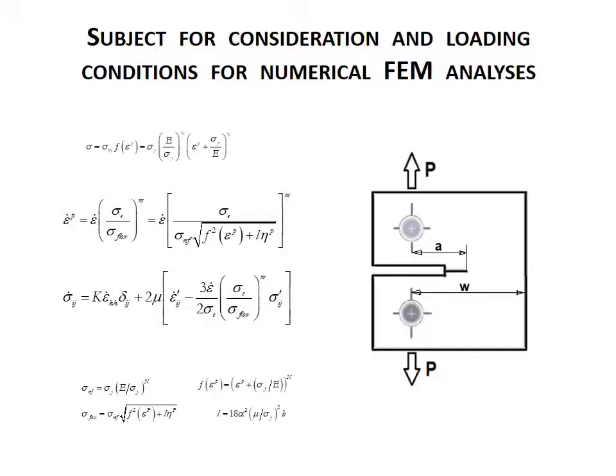The geometry considered in this study is the compact tension specimen. This specimen configuration is applied conventionally for numerical and experimental studies in fracture mechanics. We modeled the contact between the pins and the specimen by using a surface-to-surface contact algorithm with finite sliding.